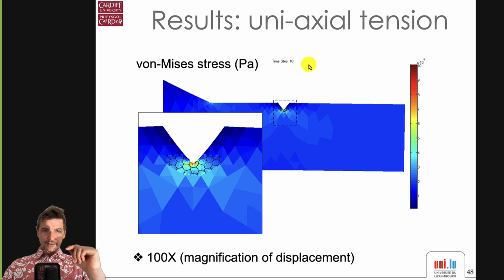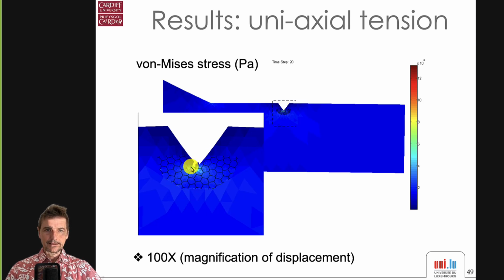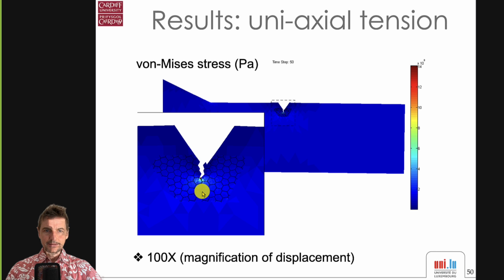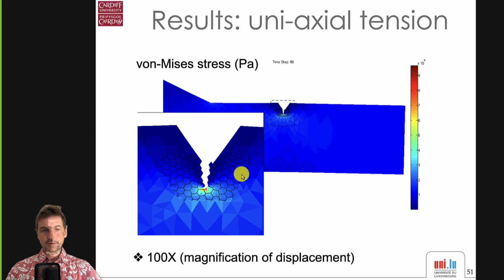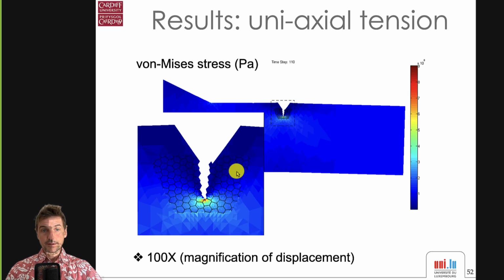So the idea here is to look at von Mises stresses in the region where the cracks initiate. We initiate with no crack. The cracks initiate only when we reach the peak, and when we reach the peak, we let the domain propagate. As you can see, the elements where the full microstructure is being taken care of move through the domain and take up more and more of the domain space.